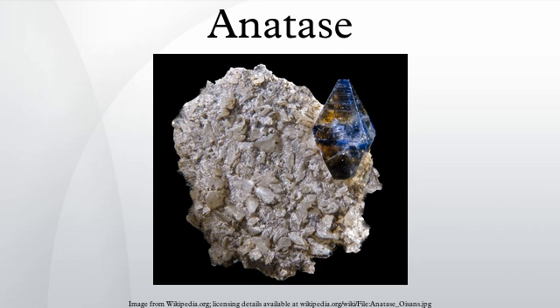Synthetic Anatase crystals can be prepared in laboratories by chemical methods such as the sol-gel method. Examples include controlled hydrolysis of titanium tetrachloride or titanium alkoxides. Such synthetic Anatase is of considerable interest for photocatalysis and for Grätzel cell photovoltaics.